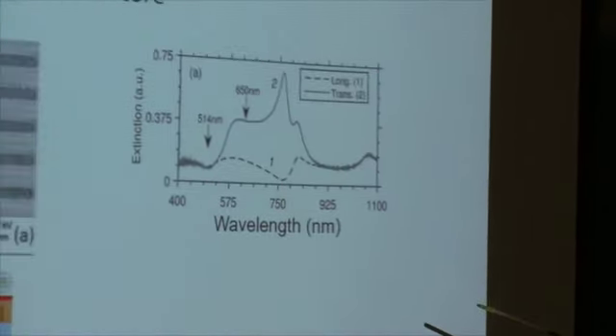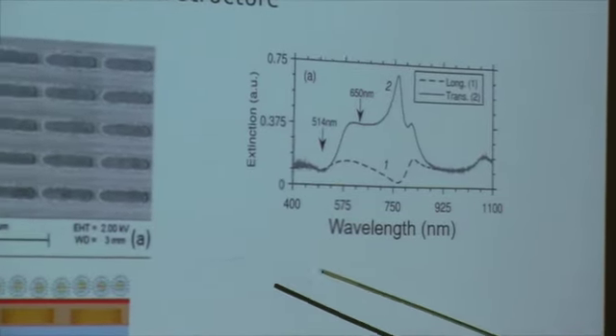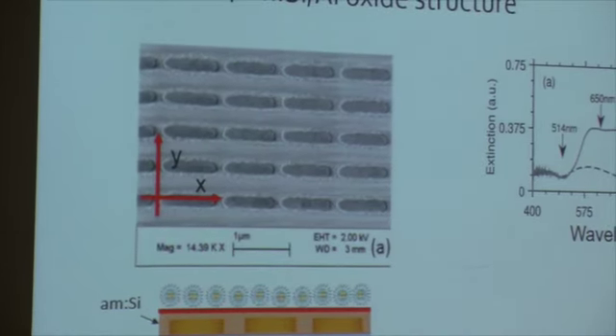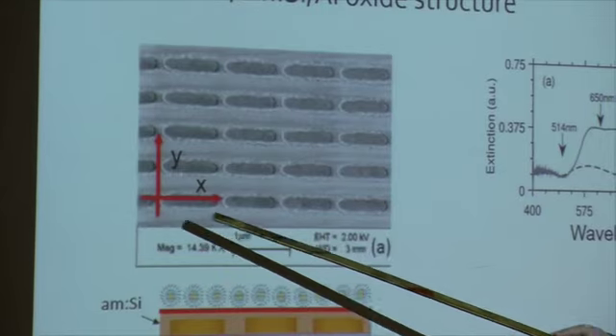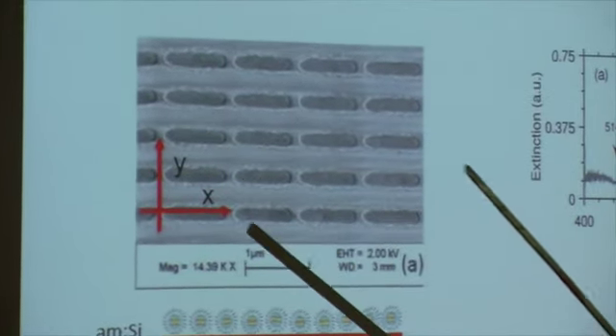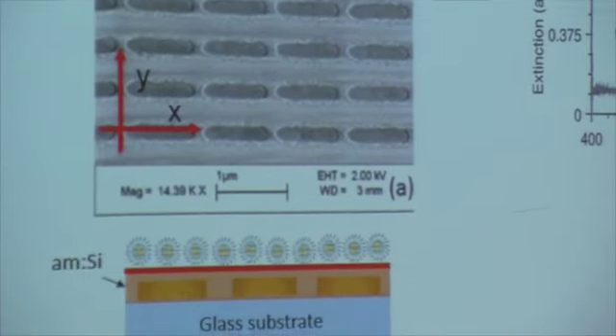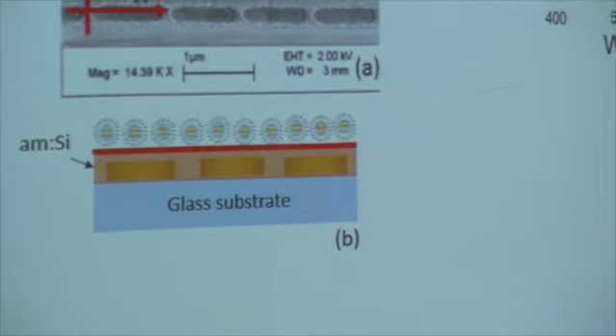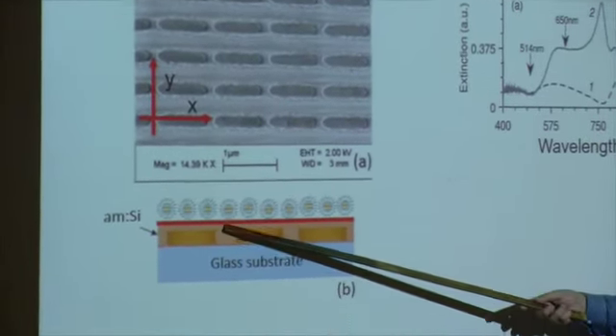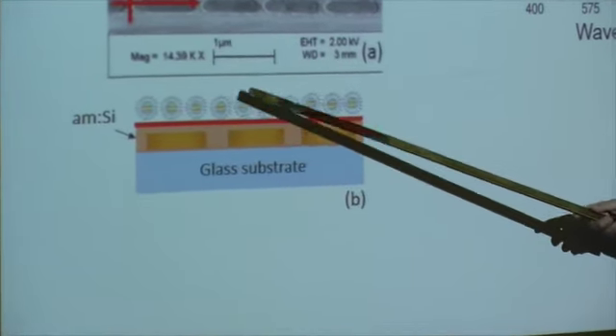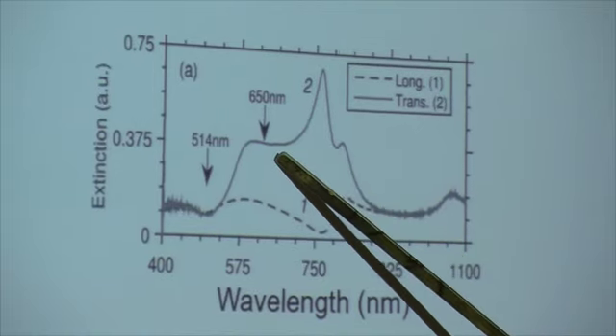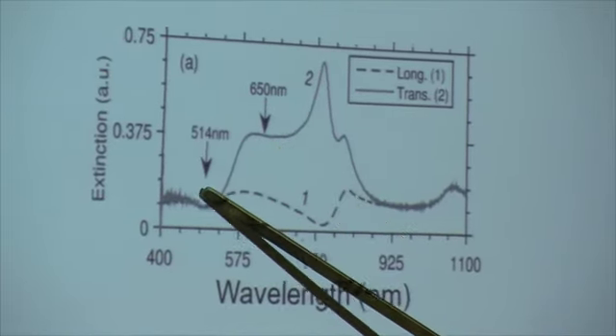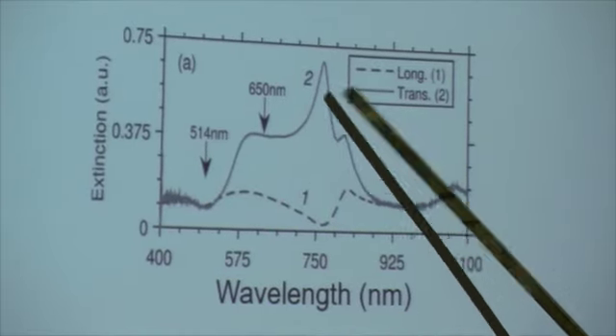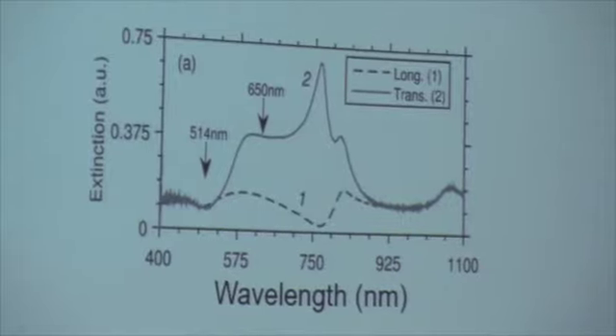Now, this is the metallic structure that we use, an array of metallic nanorods, simple. But you have to remember, we call this the x-axis, and this is the y-axis, right? Laser is coming. It doesn't matter what kind of polarization it has, because it gets absorbed in the quantum dot far from the band gap of it. And this is the structure. We have silicon with glass and quantum dot on the top. This is the extinction spectra of the metallic structure. You see that the quantum dot decays at 650. Laser comes at 514nm. And there is a peak here, which I mentioned to you, but it is not effective here. It's called SLR, surface lattice resonance, which is not playing much role here.